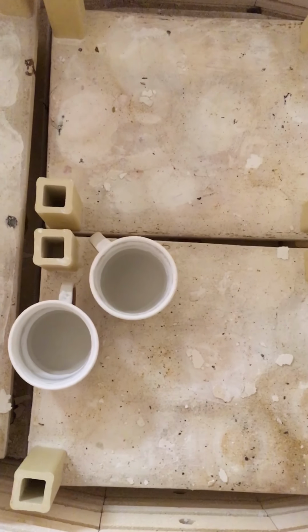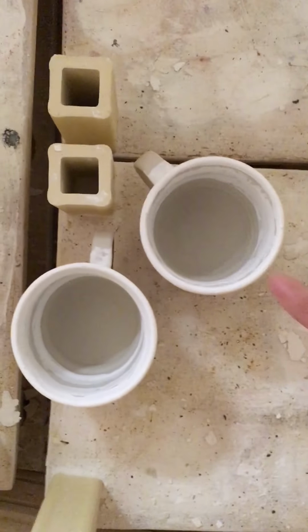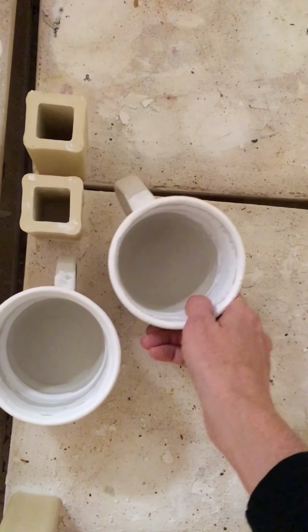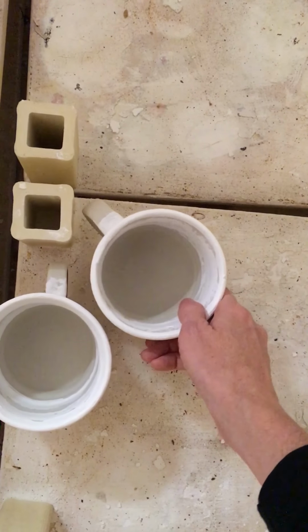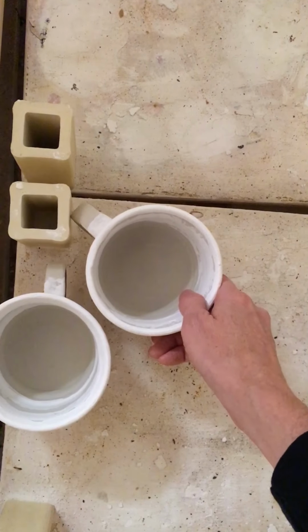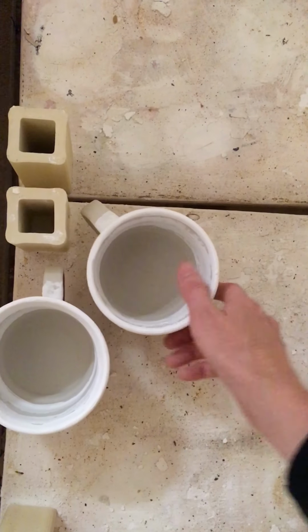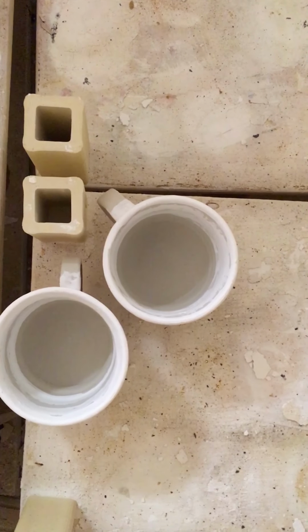These are 2 glazeware cups that I have loaded. You notice that there's nice spacing between the forms. They're not crazy wide apart. I'm still smart about my space, but you don't want them touching or they will fuse together. Don't let them touch the stilt either. It will fuse the stilt. So you want to make sure that there's a little bit of space there. Always double check before you put the next shelf on that there's space between each glaze form.